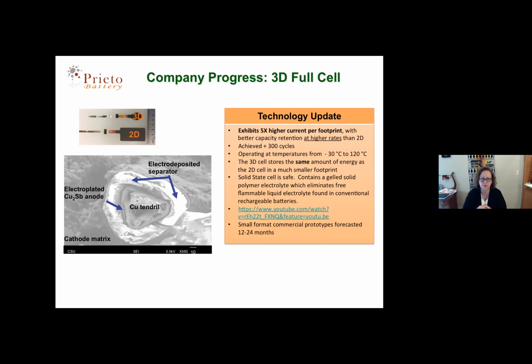When the polymer is gelled, this battery does really well at -30 degrees Celsius, and it's stable up to about 120 degrees. And if you click on that YouTube link, you'll see a video of us fully charging a battery, cutting it open, and there's no thermal runaway, no fires. The battery actually does keep working. So we've been able to combine some of the best of a true solid state battery, but by gelling the polymer, we are able to achieve low temperature performance, but still maintain some safety.